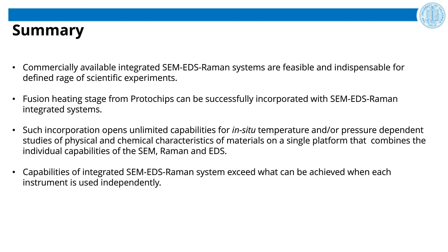What is the temperature range in which the in situ SEM chip can work? Yeah, I think I mentioned this briefly in my presentation, but you can heat up to 1200 degrees C with the system. And I think I mentioned the heating and cooling rates that were accessible with that as well. But yeah, hot enough to melt a lot of things. So 1200 C is what we can go to.